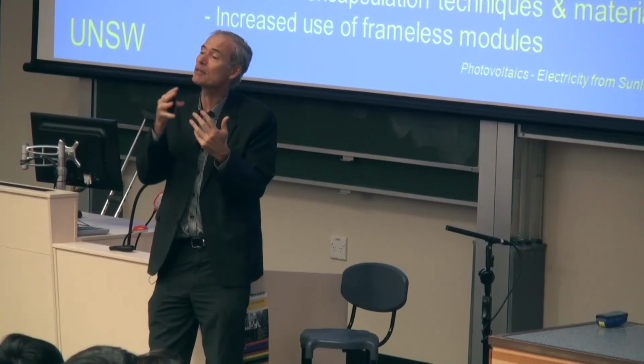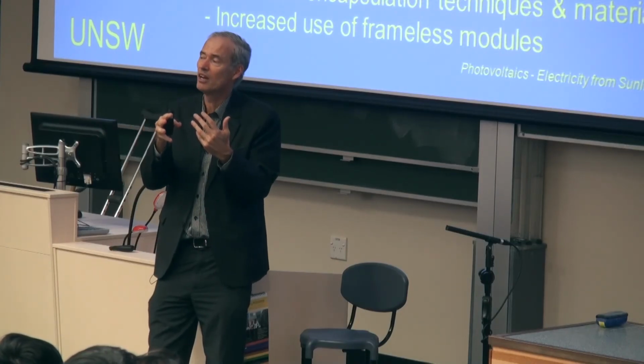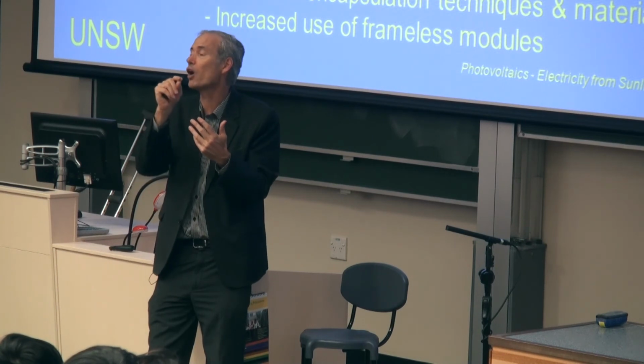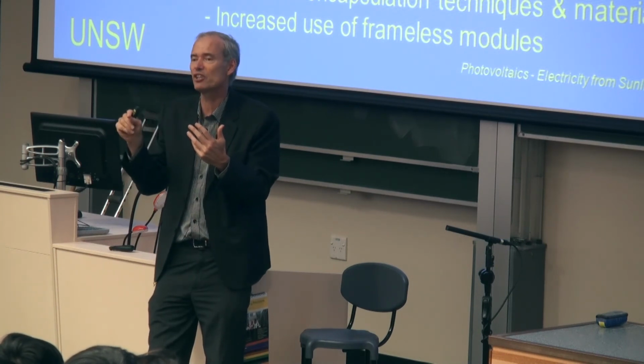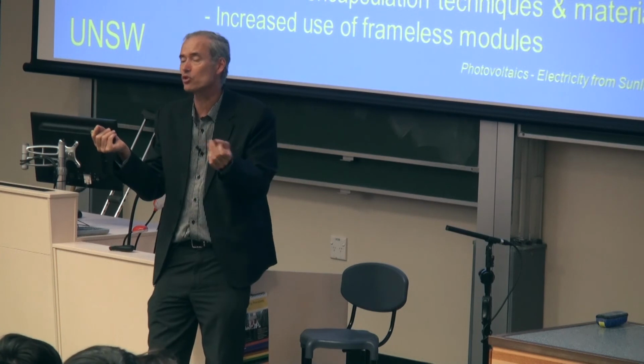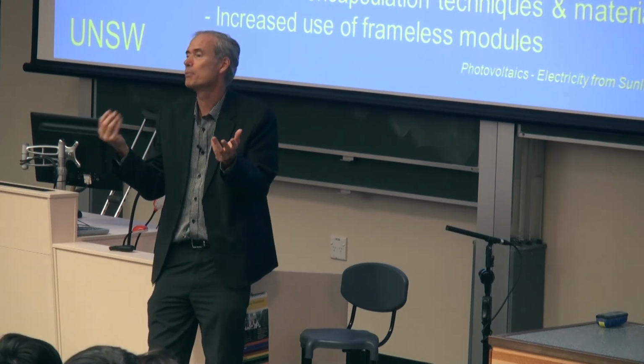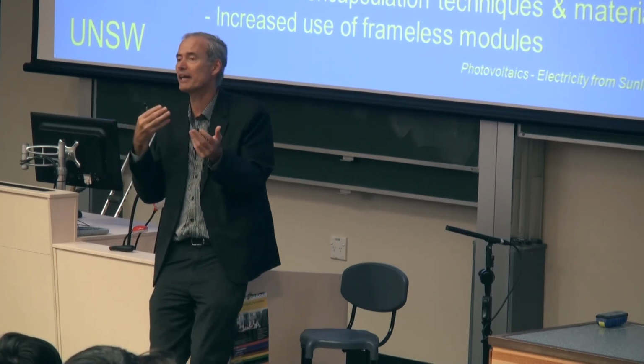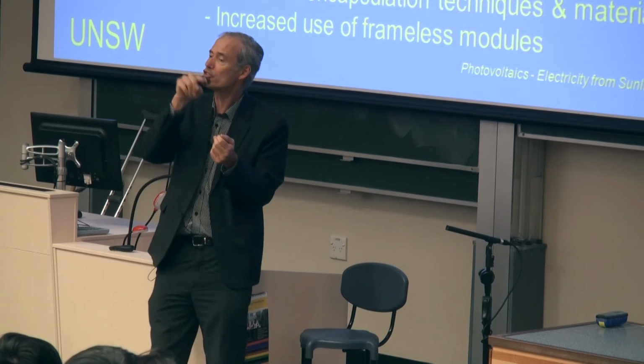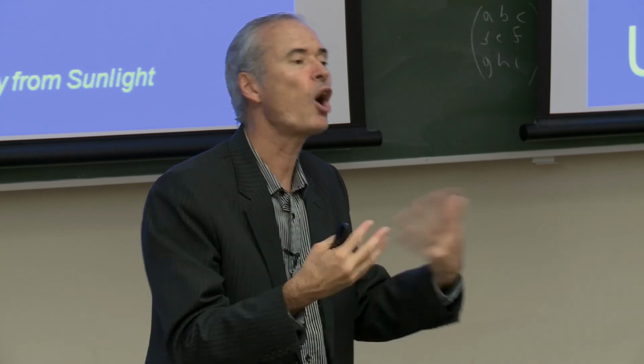And then you still have to make contact to the silicon though. And so what you then do is you have to provide patterning of that dielectric layer, either holes or lines or circles, whatever you like, but you have to enable the metal at the back to penetrate through those openings in the dielectric to contact the silicon. It's not a trivial thing. And even when you figure out how to do it, you have to be able to do it in a manufacturable way. Very high throughput with high yield and at low cost. And that's where the challenge lies.